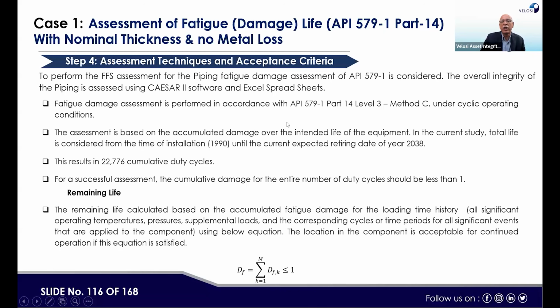Fatigue damage assessment is performed in accordance with API 579 Part 14 Level 3 Method C. The assessment is based on accumulated damage over the intended life of the equipment. In the current study, total life is considered from installation in 1990 until the current expected retiring target of 2038. This results in 22,776 cumulative duty cycles. For a successful assessment, the cumulative damage for the entire number of duty cycles should be less than 1. Next, the remaining life is calculated based on the formulas where we have to accumulate the result.